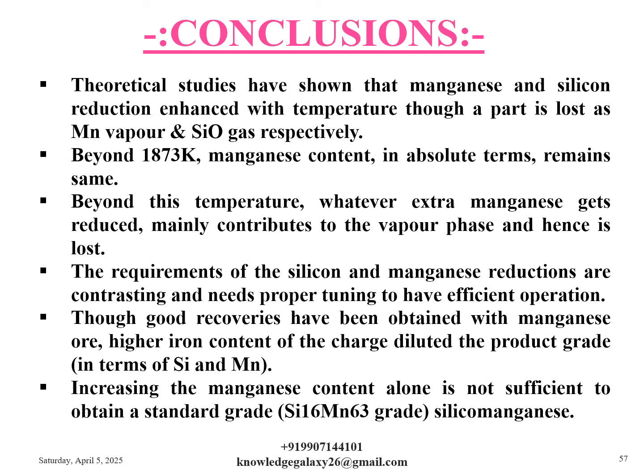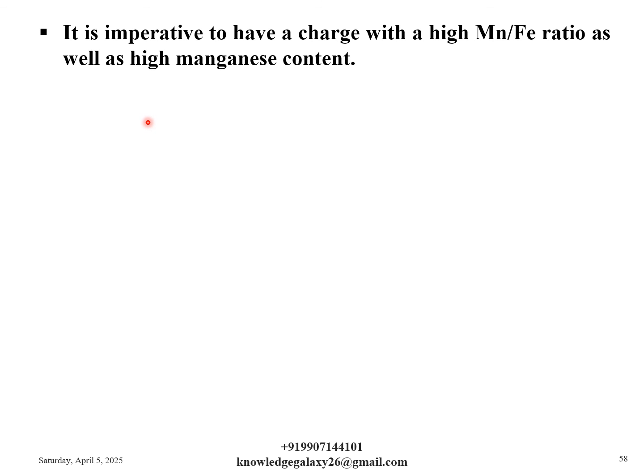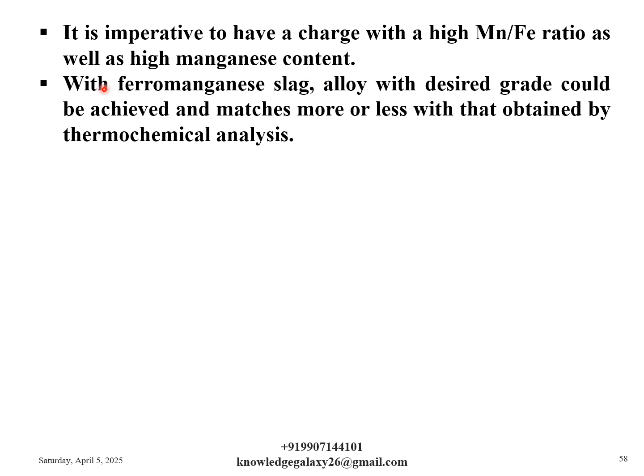And moving ahead, some more conclusions. It is imperative to have a charge with a high Mn by Fe ratio as well as high manganese content. With ferromanganese slag, alloy with desired grade could be achieved and matches more or less with that obtained by thermochemical analysis.